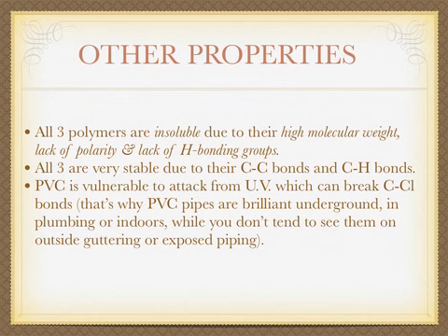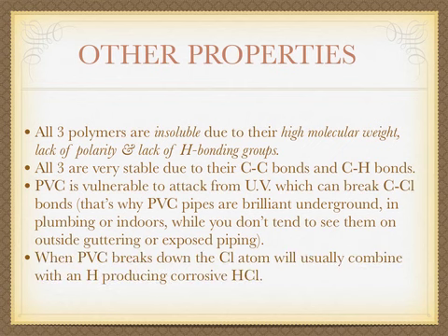Now, if you take that side chain away, you're reducing the overall stiffness of that particular polymer, and you'll notice that any PVC pipes that are left out in the sun over time will crack very easily, become brittle, and after only a few years are useless. Therefore, if PVC is used outside, you'll find that it's been painted to protect it from UV attack, and we tend to now associate PVC piping with plumbing and areas underground where there's no UV light to attack it.